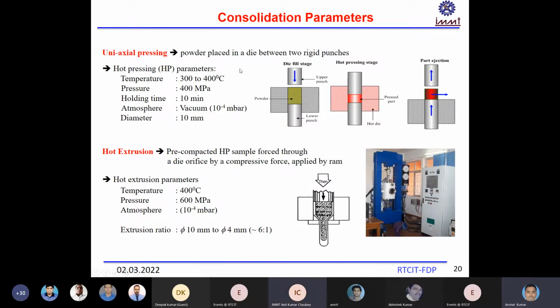These are just the parameters which were used. This is the hot press, and this is the die where the powder was filled, and then it is heated and pressed, and after that you get this cylindrical pellet, this tablet. Then this was extruded at 400-degree temperature, and the 10 mm diameter was reduced to 4 mm diameter after the extrusion, so that you get a very highly dense final component.